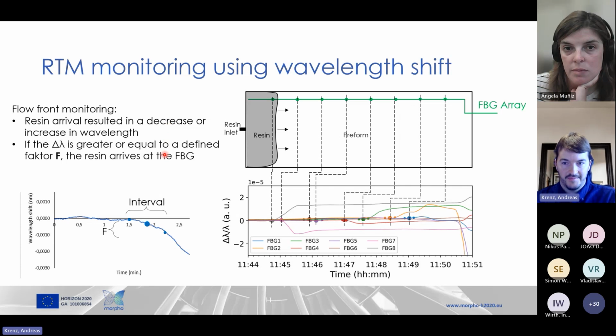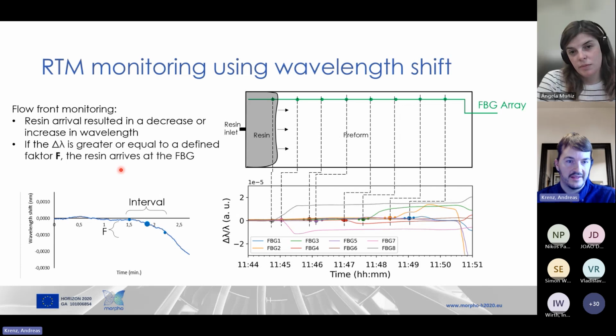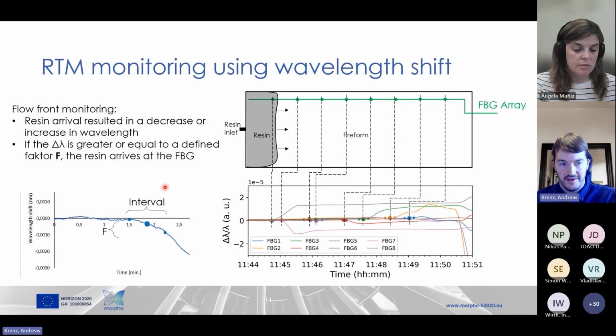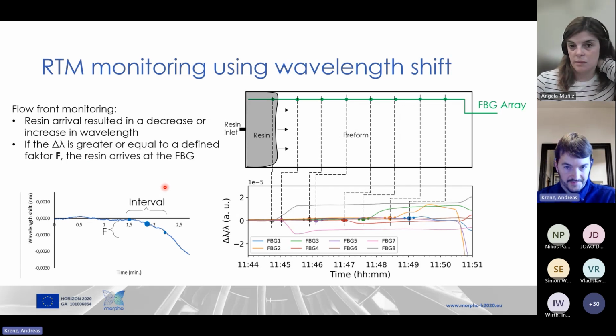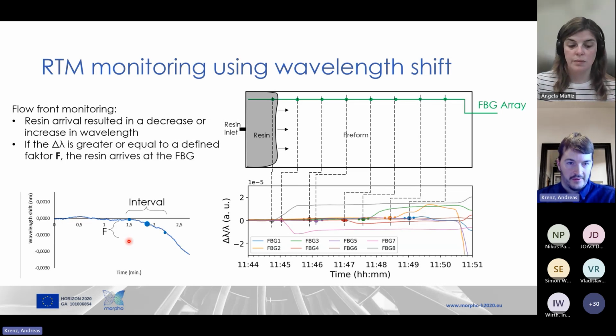It has been confirmed that the arrival of the resin resulted in a decrease, or as you see here later on, a decrease or increase in the wavelength of each sensor. And a factor based on our experimental results was used to serve as a limit value for the wavelength shift in relation to a specific interval. So if the resin arrived and the FBG at each sensing point has this wavelength shift, we can say, using this factor, that the resin arrived there.